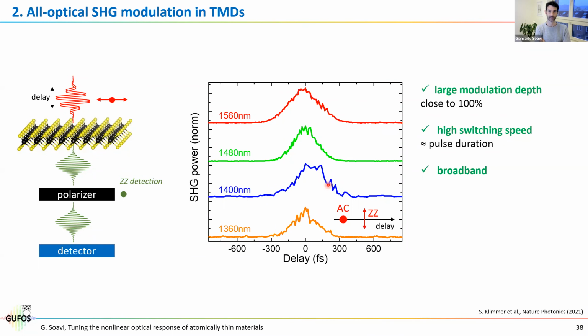We didn't see that fast degradation in the past, but I would imagine a couple of weeks, I would say. But the problem is the size. You always encapsulate it, right? Or no? We're just transferring by PDMS. But some people said, okay, PDMS protects. There is always this residue layer, so maybe it helps. Even when you remove the PDMS, you still keep it.